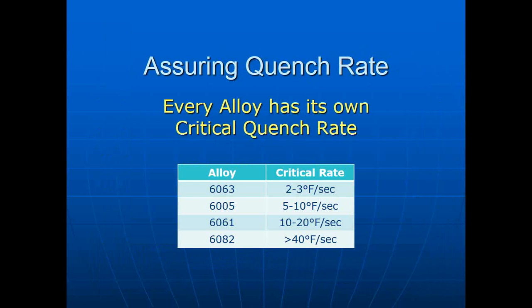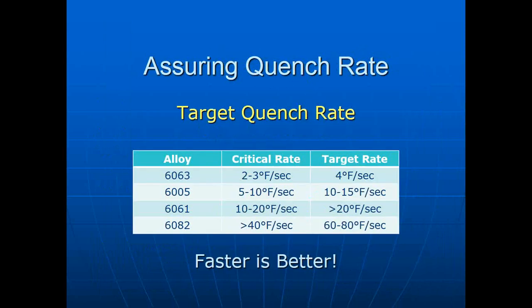There are some new extrusion alloys coming out that have even higher requirements. We're seeing requirements in excess of 100 degrees per second with certain specialty alloys. As before, faster is better. Our targeted quench rate is typically double the critical rate because we don't want to get anywhere near the point of the C-curve. When we get near the C-curve, we're threatening our final mechanical properties.